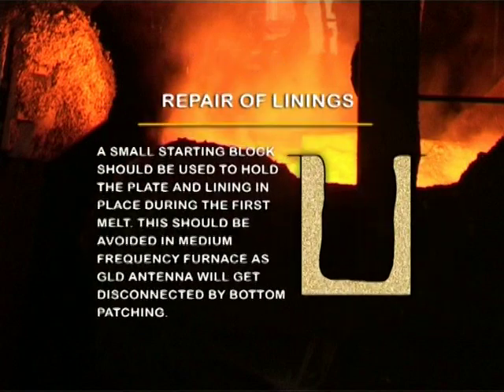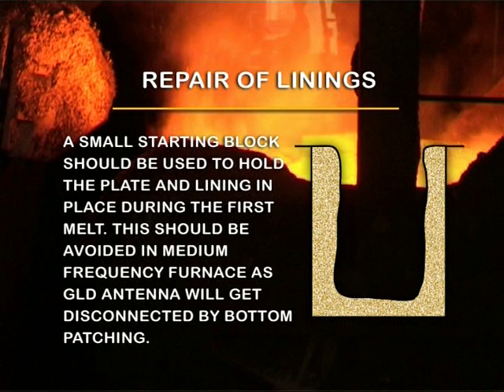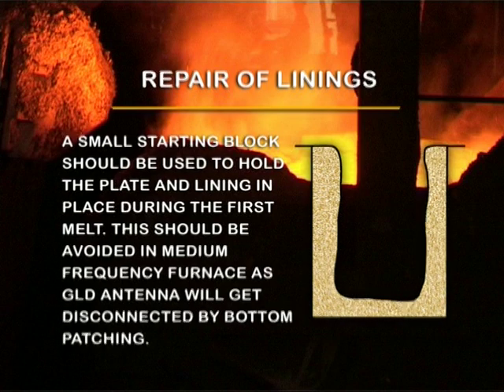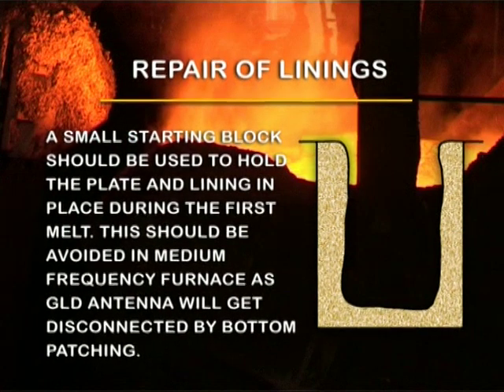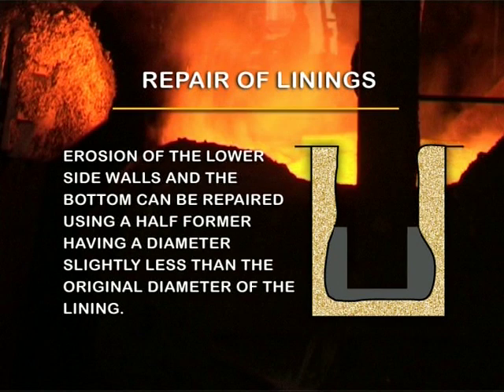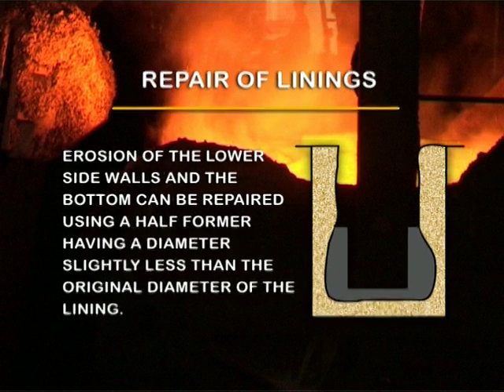A small starting block should be used to hold the plate and lining in place during the first melt. This should be avoided in medium frequency furnaces as the GLD antenna will get disconnected by bottom patching. Erosion of the lower side walls and the bottom can be repaired using a half former having a diameter slightly less than the original diameter of the lining.